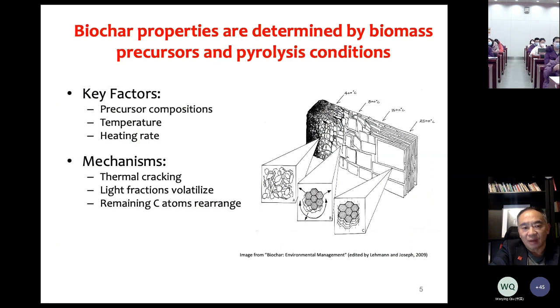So it is well known that biochar properties are determined by biomass precursors as well as pyrolysis conditions. In the case of thermal pyrolysis, it depends very much on the precursor composition, temperature, and heating rate, which is extremely important as well. The mechanisms involved include thermal cracking of those biopolymers, condensation, and rearrangement of carbon atoms. So if we look at this diagram here, you can see that with the increase of temperature, graphitic structure can be formed.